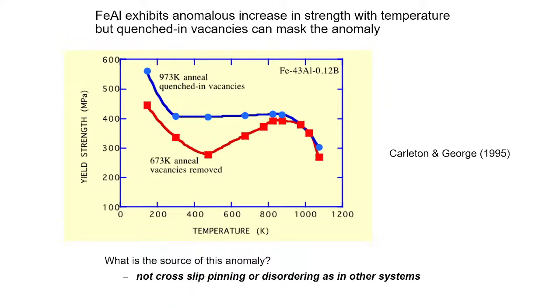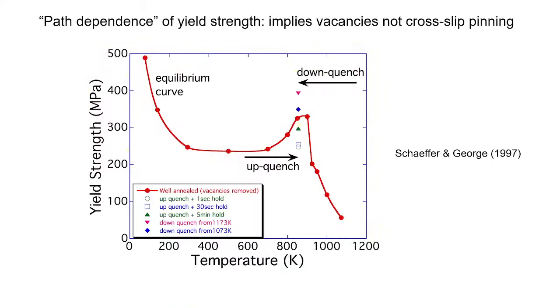But when you do that, what you find is that you get this anomalous behavior, right? So immediately our question was, is this because you're generating new vacancies? You've got rid of the vacancies, but during the heat up to the testing temperature, you're generating new vacancies. And is that the reason for this increase in strength? And sure enough, it is. The way we showed it was by doing path-dependent experiments. So if you want to test at a given peak temperature, you could approach it from the high temperature side, or you could approach it from the low temperature side, right?